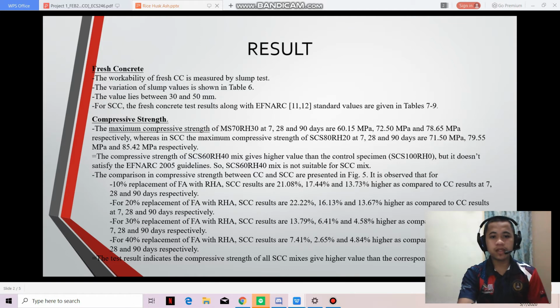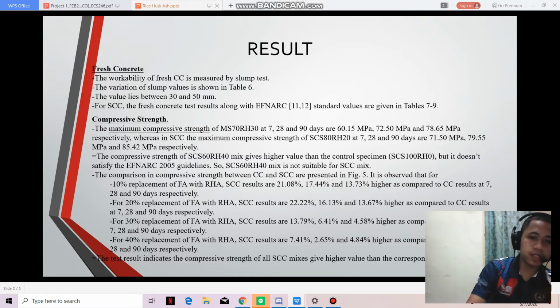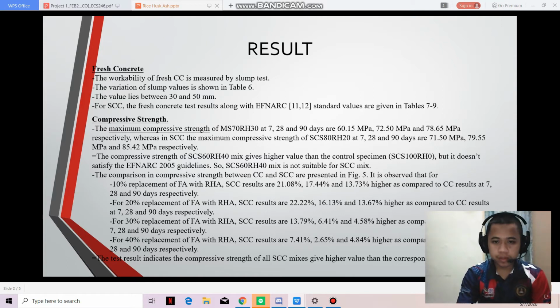And for the compressive strength comparison for 10% to 40%, this one is for 10% replacement. And for 20%, 22.22, 16.13 and 13.67, and for 30%, 13.79, 6.41 and 4.58, and the last one, 40%, is 7.41, 2.65 and 4.84.